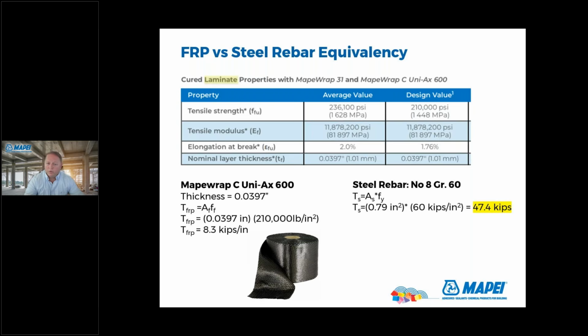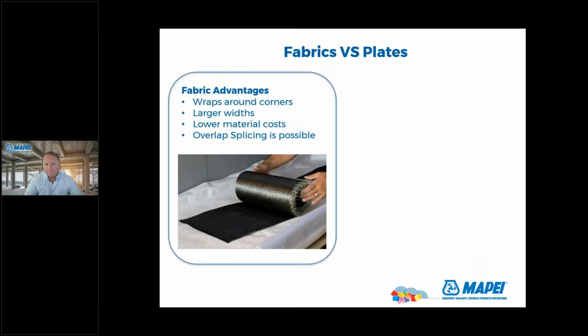Now, if you wanted to compare that to rebar, you're going to take the same type of equation, the area of the steel times the strength of the steel. So, a number 8 bar, grade 60 steel, 0.79 inches times the 60 KSI is going to be 47 kips. So how many inches of fabric do I need to kind of equal out this, just for comparison? About a 6-inch wide strip is going to give you the same amount of kips as you would get from a number 8 bar. So materials are incredibly strong.